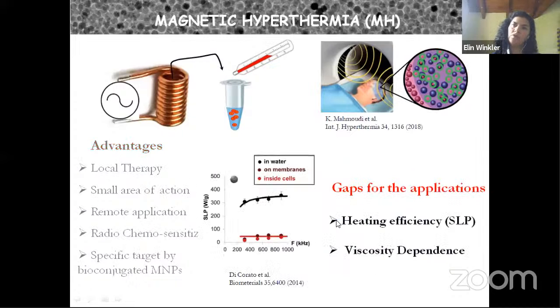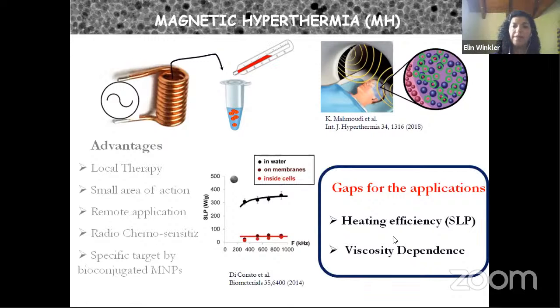In order for the method to become widespread, we need to improve many things. One of the things that has to be improved is the heating efficiency. Because of the possible toxicity of the nanoparticles, the agency that regulates the application of drugs requires that you can use only a very low concentration of nanoparticles. So the heating efficiency should be improved. And also, when you do the experiment in the lab, you frequently observe that the nanoparticles induce heating of the material, but then when you internalize the nanoparticles in the cells, the specific power absorption drops. So we need to fabricate a material that is independent of the viscosity.